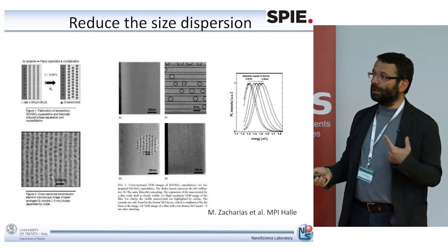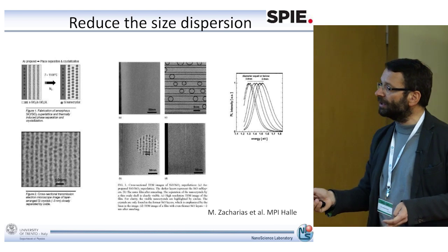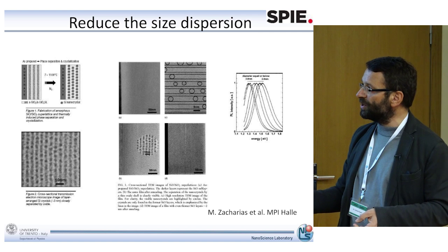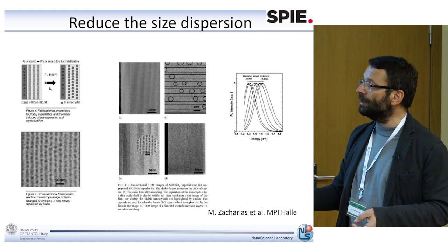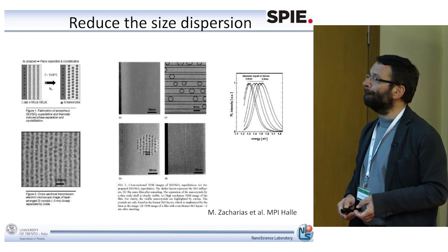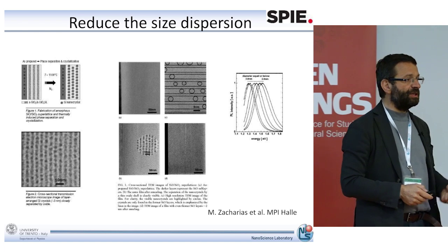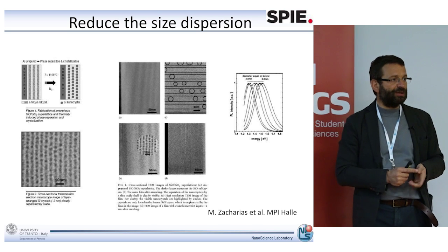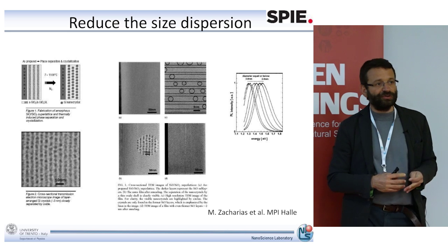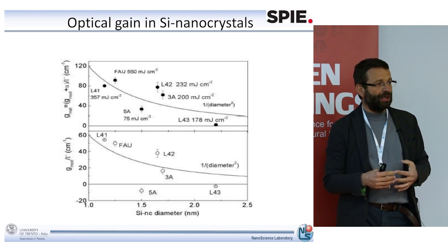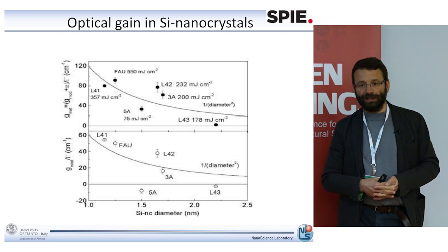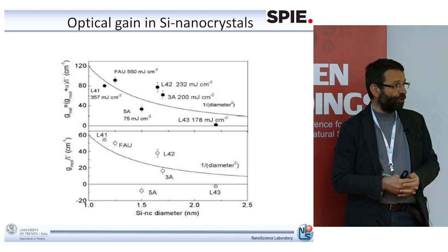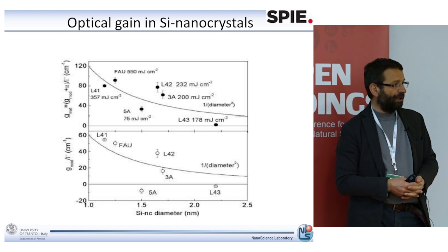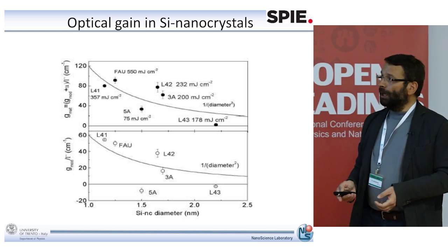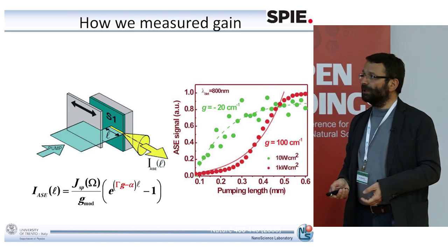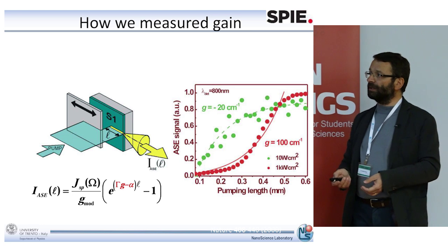Here is an example. In this case, the thickness of the layer is 5 nanometer, which means that the nanocrystal now have a typical size of 5 nanometer. Good. One thing that is even more interesting as a result of the quantum confinement is the fact that by using silicon nanocrystal, it is possible to get not only emission, luminescence, from the silicon nanocrystal, but also stimulated emission, so gain, optical gain in the silicon nanocrystal. This is what we did in order to observe the optical gain. So let me talk about this experiment that is much easier to understand.